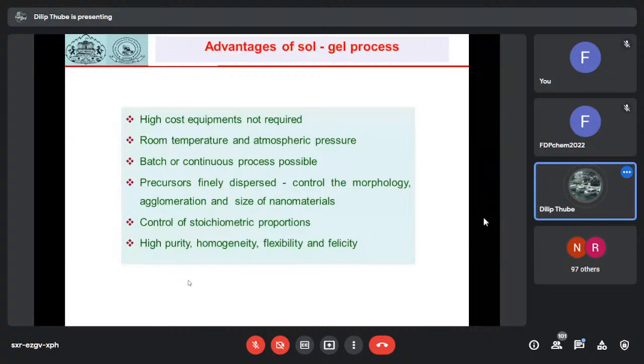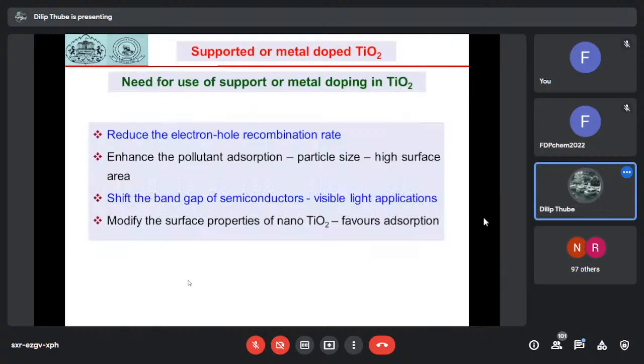So high cost equipments are not required for this process. This process can be carried out at room temperature as well as under atmospheric conditions. This process can be carried out in a batch as well as continuous manner. Precursors which are used for the synthesis of materials can be finely dispersed, and therefore the morphology of the nanoparticles can be controlled as well as their agglomeration, and nanoparticles of the desired size can be obtained through control of the stoichiometric proportions. Therefore, high purity as well as homogeneous nanoparticles can be obtained.